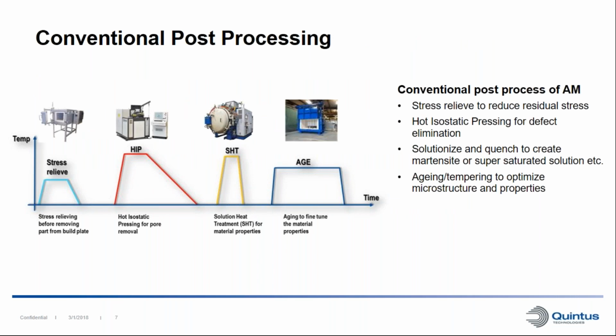So if we look at this picture here, we have schematics over a conventional post-processing route. And in this case, it's towards an additive manufactured part. It can also be a casting or a MIM part, for example. So we might have a stress relief step here to reduce the residual stresses in the part. Then we have a HIP step to eliminate internal porosity. If it's an old HIP system, we would have a relatively slow cooling rate. After the HIP step, we would normally have a solutionized treatment where we have normally a very close temperature to the HIP temperature, if not the same temperature. In this step, we normally have a high cooling rate, and then we might have an aging or tempering step afterwards.